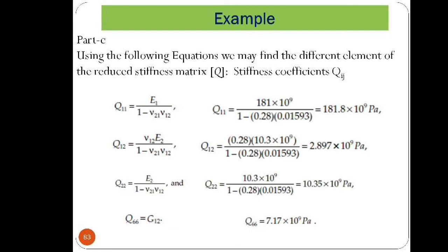Similarly, we may calculate the stiffness coefficient corresponding to the in-plane shear stress, G12, and that is 7.17 into 10 to the power 9 Pascal.